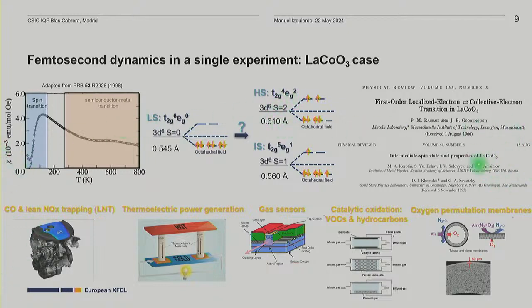However, in the 90s, LDA calculations using correlations with a U factor of 7 proposed a different model, a possible transition to an intermediate spin state, S1. Basically, you have 5 electrons in the T2G orbitals and 1 electron in the EG orbitals, and the ionic radius is in between.